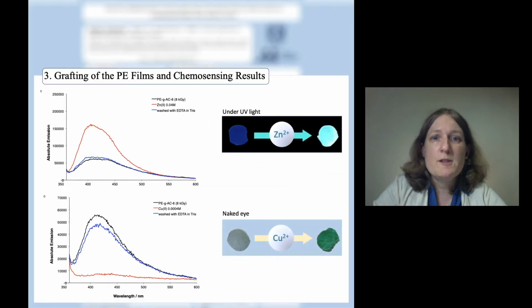The grafted polyethylene films were used as chemosensors for zinc and copper ions. An increase in the fluorescence emission was observed after submersion of the polyethylene films in a solution containing zinc ions. The film was washed with EDTA and the initial spectra was recovered.